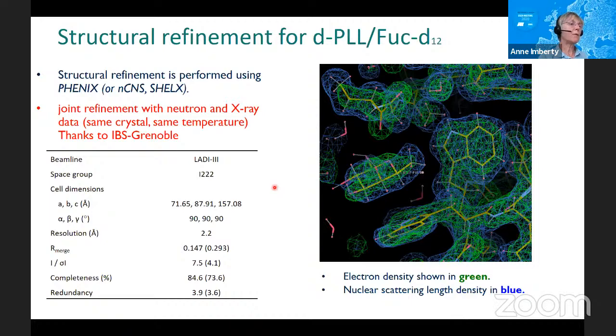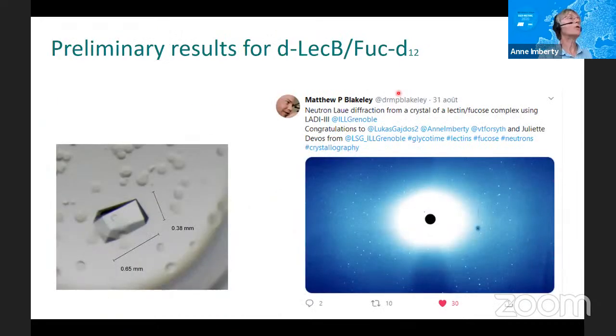So this story now is on the last step of refinement, and in parallel, we continue on the lectin from Pseudomonas. In fact, the big crystals that took 6 months to grow had too much mosaicity at the end, and we had to turn to a smaller crystal. But you see that even with this reasonably sized crystal, it was quite good.